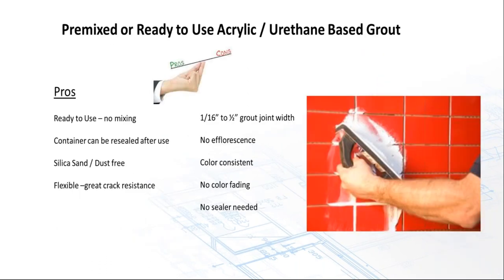So what are the pros of the ready-to-use grout? No mixing. Container can be resealed after use. Silica sand, dust-free. We know the silica has been an issue, specifically the last 4 or 5 years. It's come up quite a bit, so big advantage there. Flexible, great crack resistance, 1/16 to a half an inch. So again, have one product on the job site. No efflorescence, because it's not a Portland cement-based product. Color consistent, no color fading, no sealer needed.